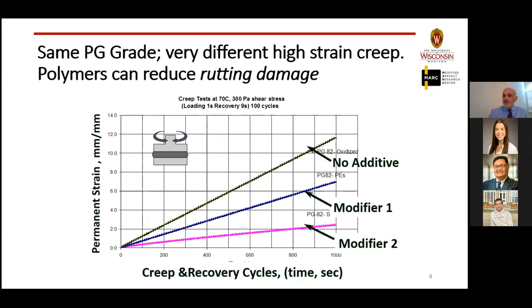This is a creep and recovery test in the DSR, the same tool that we use for measuring G star over sine delta, but G star over sine delta is limited to this region, the very small stress and strain. When we took the permanent strain in the binder to much larger levels, in this case, this is the number of cycles or the time we have loaded them, we started seeing very significant differentiation between three binders of the same grade. This is an oxidized binder, no polymers in it. This is another binder with some polymers of a certain type, and this is a third one.